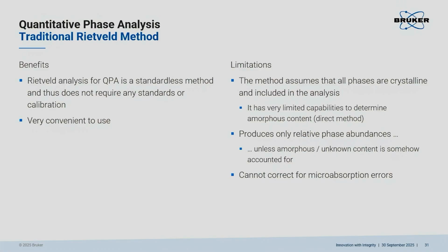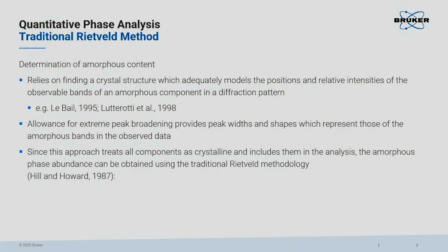It has very limited modeling capabilities of amorphous content. I will show you an example in a second, but I would rather say, even though I show you a working example, you cannot use the traditional Rietveld method for quantification of amorphous content in general. Exceptions confirm the rule sometimes. Very important, again and again, it only produces relative phase amounts. Very important. It cannot correct for microabsorption effects, also important. No calibration, no microabsorption correction.